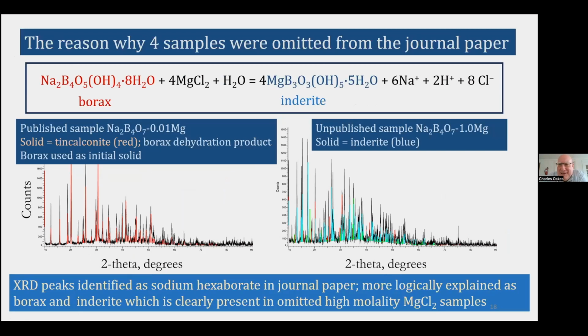This is what happened. Those samples are something different. This XRD scan on the left is from another government report, the same samples. It is an XRD scan of the most dilute magnesium chloride solution, one of the samples that was published. And if you look at the XRD scan, all of the peaks match up with the reference standard peaks for a mineral called tincalconite. Well, tincalconite is a dehydration product of borax. You can produce it during the sample preparation for the X-ray diffraction analysis.